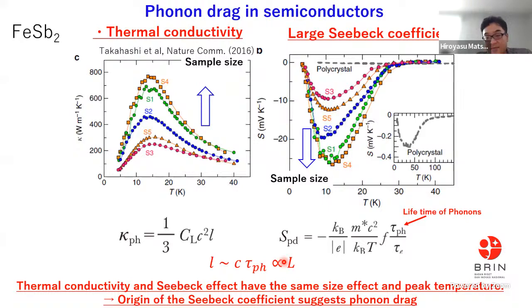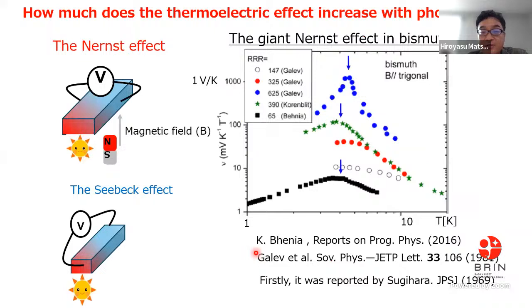Therefore, if we use a large sample, we can get a large L, and finally we can get a large kappa. And the Seebeck coefficient also has this tau. Tau is proportional to size. So in the large size case, we can get a large Seebeck coefficient. This behavior is coming from the sample size. So the important point is that in the semiconductor case, we have the sample dependence in phonon drag.